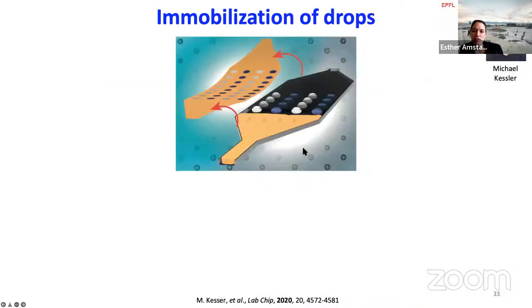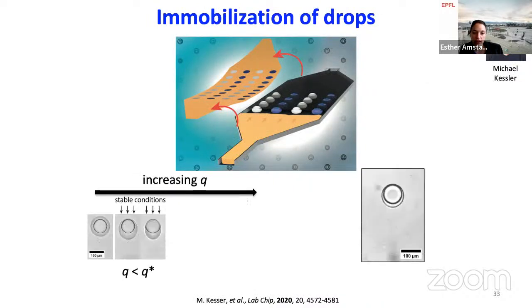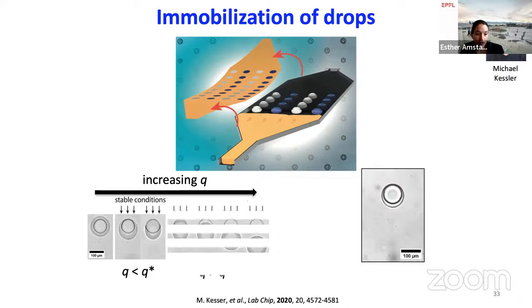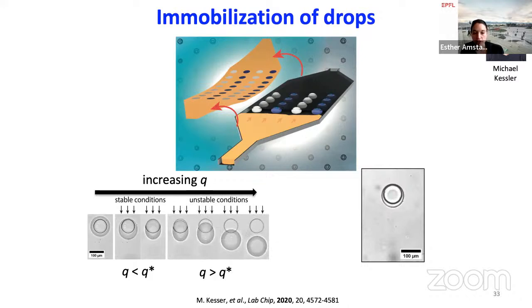composition, we actually designed microfluidic trapping devices that have different trapping strength. So basically the way that it works is you have a thin chamber whose height is smaller than the diameter of the drop. So the drops are squeezed. And within this chamber, you design traps where the height of the channel abruptly increases. And as soon as the drop hits such a trap, it can relax, it can expand into the height in the z direction, and thereby it reduces its surface area and thereby surface energy, and that results in a trapping force. And as long as the shear force that is applied to the drops by the surrounding fluid is lower than this trapping force, the drop stays put. As soon as the drag of the fluid is higher than this trapping force, the drop is removed.